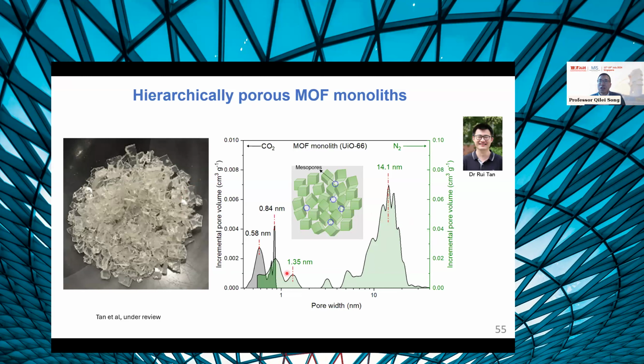But the challenge is metal organic frameworks are relatively brittle, right? If you want to make membranes from MOF materials, people normally use mixed matrix membranes, but mixed matrix membranes are limited by the polymers. The transport of gas and ions is limited by the polymer matrix itself. So we were thinking, can we engineer this MOF monolith into freestanding MOF membranes or separators?